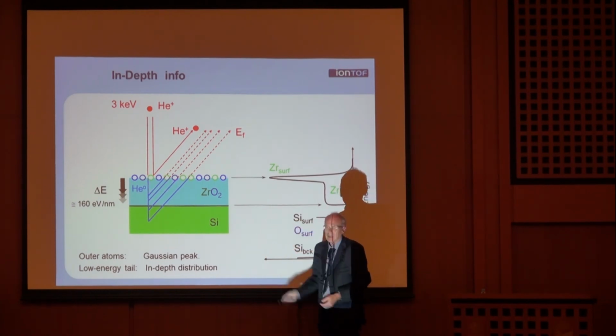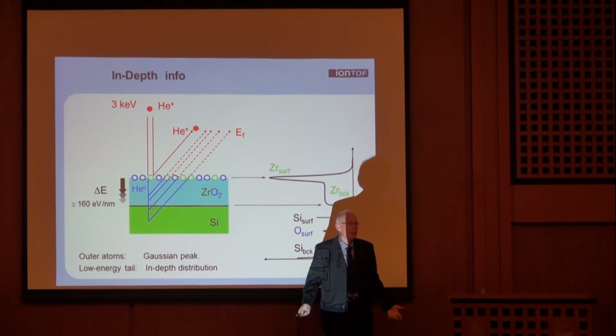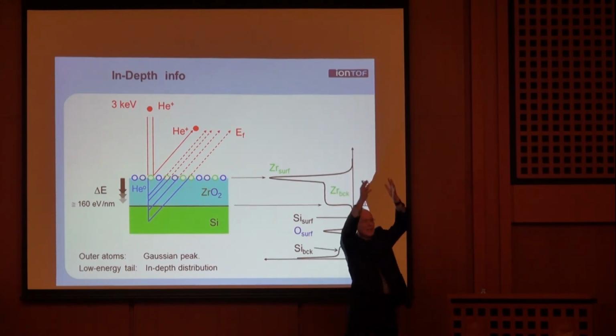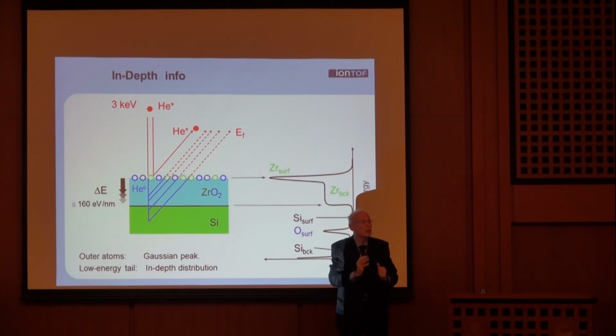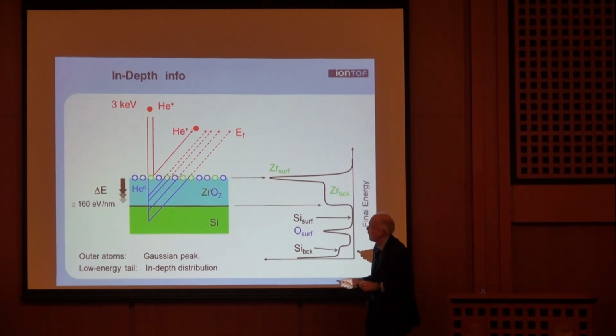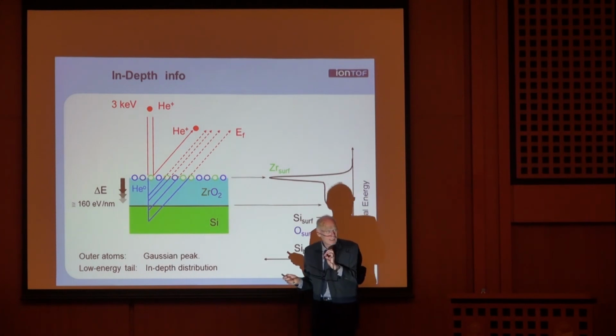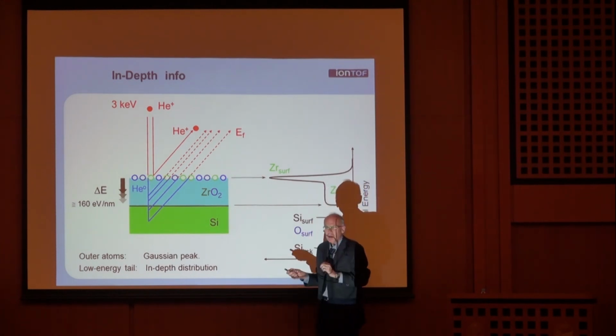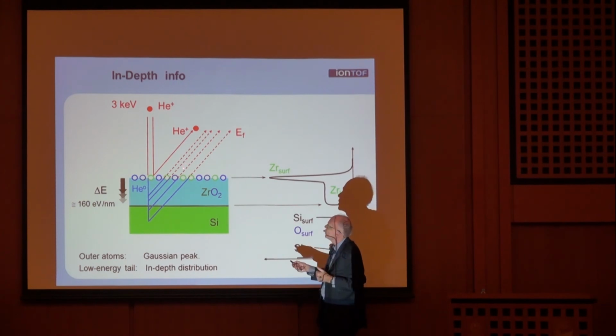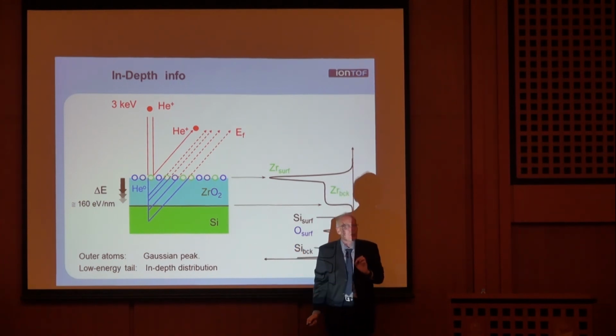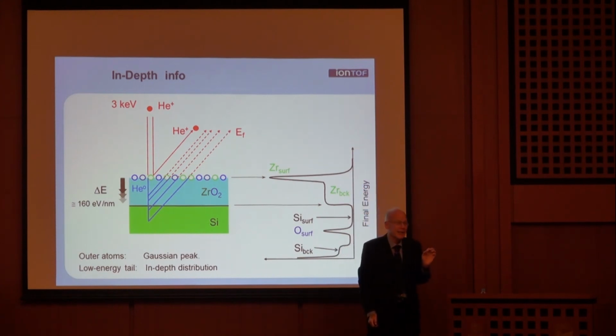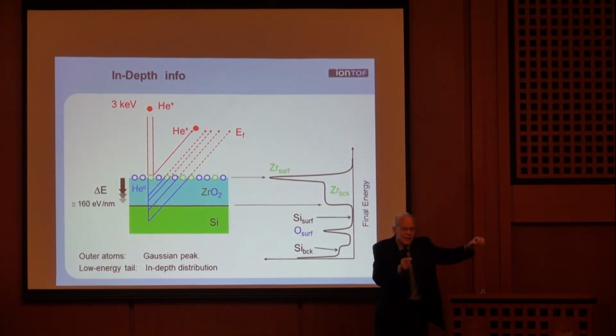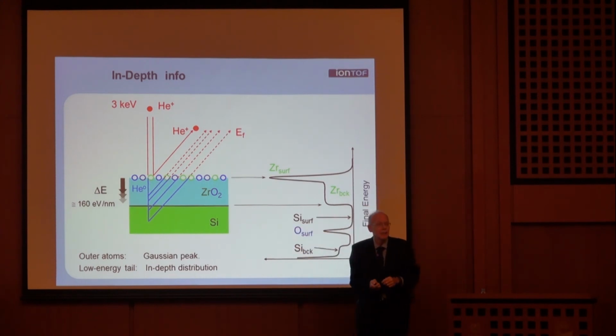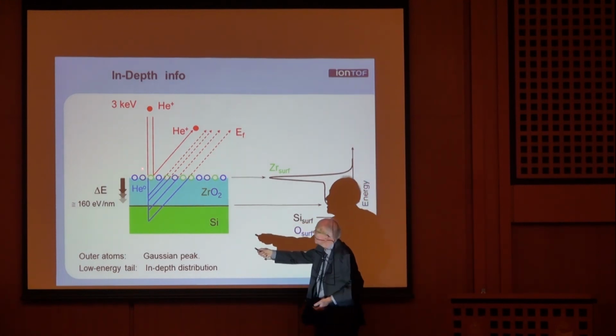If it would stay neutral, I cannot see it because I need this zigzag in my analyzer, and I can only do that with electrostatic fields. But fortunately, there are thresholds, and above a certain threshold, there's a small probability to be re-ionized again. So, for instance, helium in a last collision with an oxygen atom, above 700 volts, gets re-ionized. And in that way, I can make visible deeper layers.